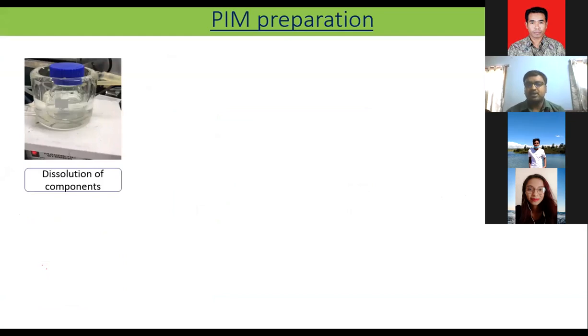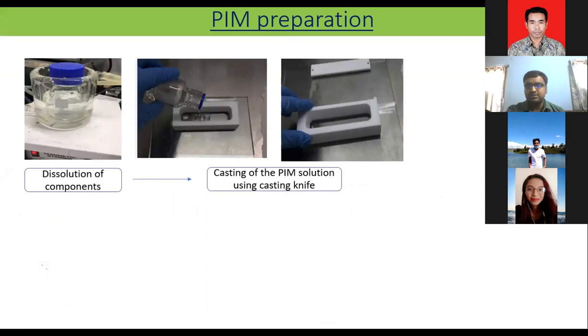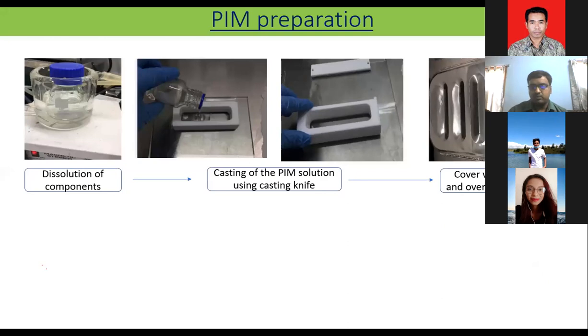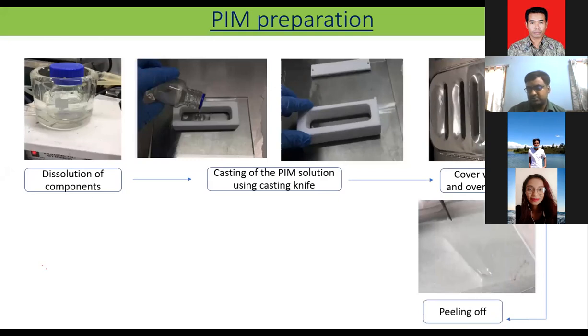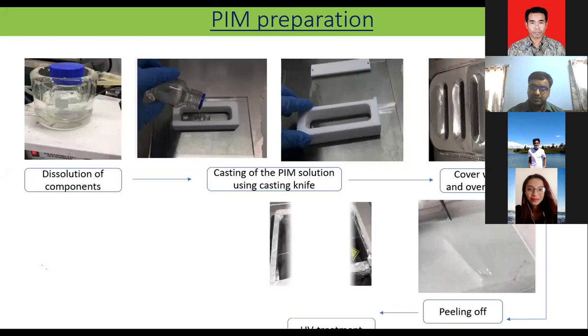In my case, I prepared the membrane in a slightly different way than Fidel. They used a glass ring for casting the membrane, while I used a casting knife. We cleaned a glass plate, put the solution inside the casting knife and dragged it, and then covered it with aluminum foil for slow evaporation of the organic solvent. In 24 hours, we get a dry, transparent membrane, and peel it off from the glass plate.